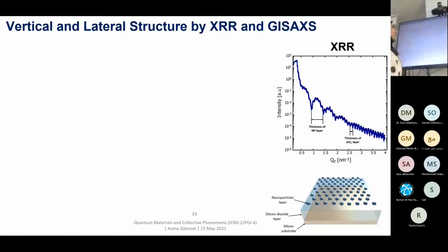In order to understand the out-of-plane ordering of these particles, an X-ray reflectometry measurement was performed, and from it we obtained two different oscillations. The big oscillation corresponds in real space to the smaller thickness, which is our nanoparticle thickness in this case, and the small oscillation corresponds to the larger thickness, which is our oxide layer below the nanoparticle layer, around 50 nanometers.